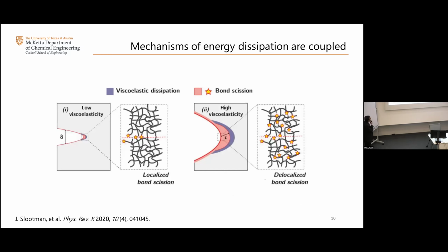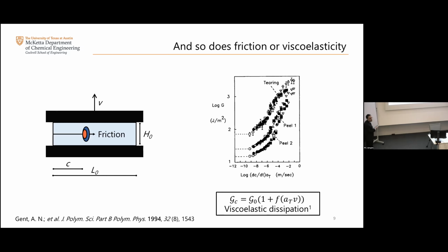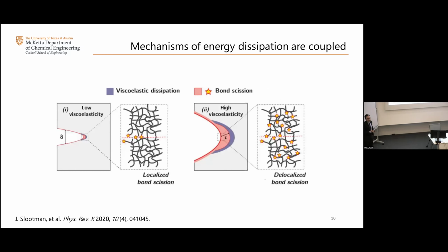Very recently, work coming out of Constantino's group has shown that the situation is a little bit more complex, in the sense that these two things are not necessarily decoupled. As a matter of fact, they are coupled. When you are in a limit where you have low viscoelasticity, you have low damage because the crack tip opening displacement, or the local deformation ahead of the crack tip, is very small. Whereas when you have very high viscoelasticity, your crack is more blunted, you have a larger damage zone, more friction. So in reality, things are not as simple. You actually have coupling. Okay, so this is what we understand in terms of energy dissipation.